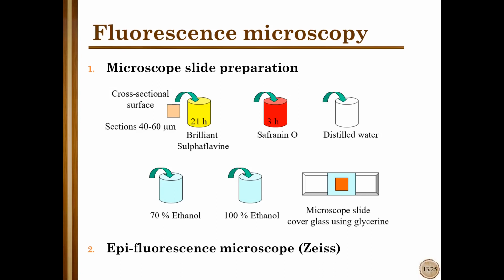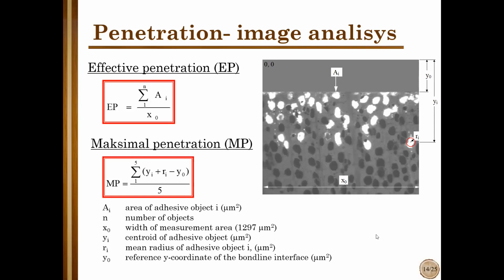Then we stained those samples with different stains like brilliant sulfaflavine and safranin O. Then we prepared microscopic slides and used epifluorescence microscopy for analysis. This is the examination of adhesive penetration in two different ways. One was so-called effective penetration, which is an equation that puts all those areas of adhesive spots together, and this is divided by the width of the observed image. Effective penetration is much smaller compared to maximal penetration.